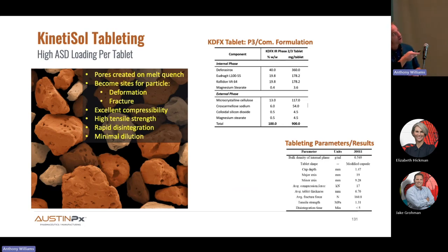But if you look closely, there are pores in these granules throughout. And these pores are generated during the quenching operation where there's air entrapment. As you'll see tomorrow, when the material exits the compounder, it's got the consistency of Play-Doh, and then it's rapidly quenched through a compression operation to bring it down to close to room temperature. And in that quenching operation, some of the air is retained. And those pores are points for plastic deformation and brittle fracture. So that is what allows KinetiSol material to be significantly more compressible than similar thermally processed materials. So we have good compressibility with the KinetiSol granules, even without a lot of external phase excipients. So this is what allows us to, with minimal dilution, arrive at really acceptable tablets.